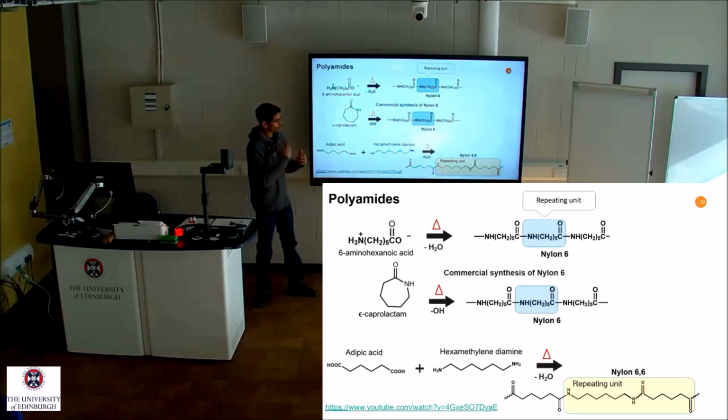So in order to continue the reaction, you have to remove the product from there, so that further solution of the organic layer and aqueous layer can come close to each other and continue the reaction. So this is one of the characteristics of interfacial polymerization. You always have to remove the polymer from the system in order to continue the reaction.